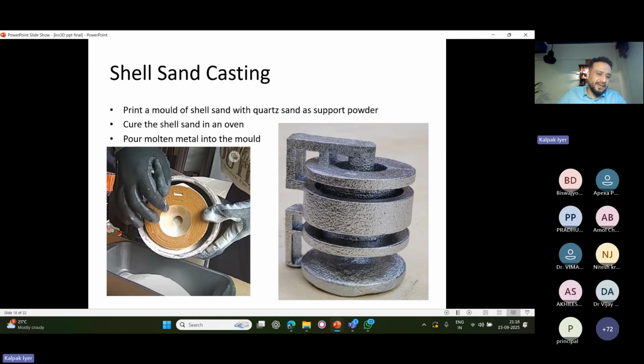We only started off with metals and glass, but here we have shell sand molds, and now we have started to have industrial applications of this. Basically, we use resin sand as the build powder, and we use a silica or an alumina sand as a support powder. We do the SPD 3D printing. We put the crucible inside the oven or the furnace. We heat it to about 200 degrees Celsius. The resin sand forms a single piece mold or a core. Then we melt some metal and put it into the sand mold, and we obtain the part. This is the part that we obtain through SPD printing. This was the first part, in fact.